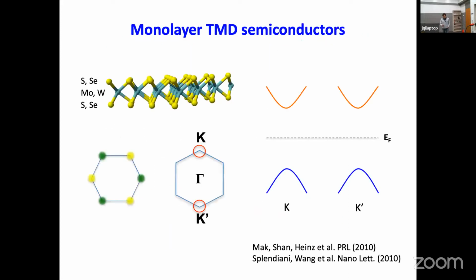All right. So just a very brief introduction of the building block material that we use to make this Moiré material. It is a monolayer of this transition metal dichalcogenide, or TMD, semiconductor. So this is the structure of one of these layers. It has 3 layers of atoms with the middle layer of transition metal atoms sandwiched between the top and the bottom chalcogen atoms. Typically, this is molybdenum or tungsten in the middle, and sulfur, selenium, or tellurium at the top and bottom. And if you look top down, it's actually like a graphene lattice. It looks something like this, except that the A and the B sublattice sites are now occupied by different atoms. So the inversion symmetry is broken.